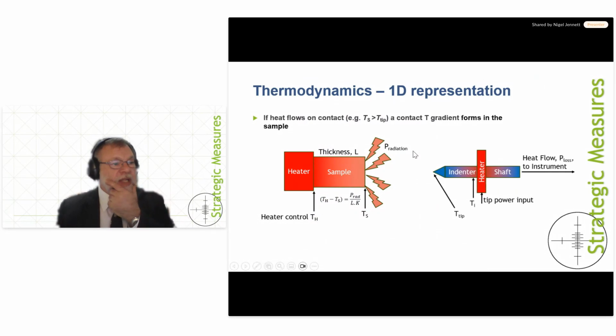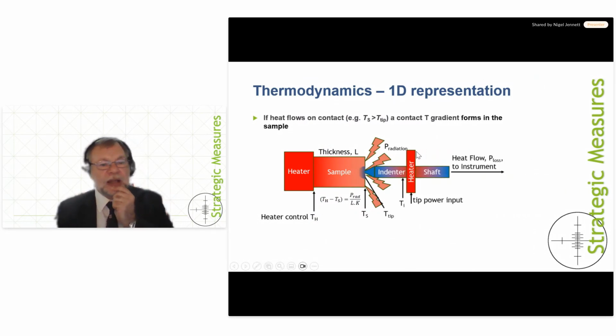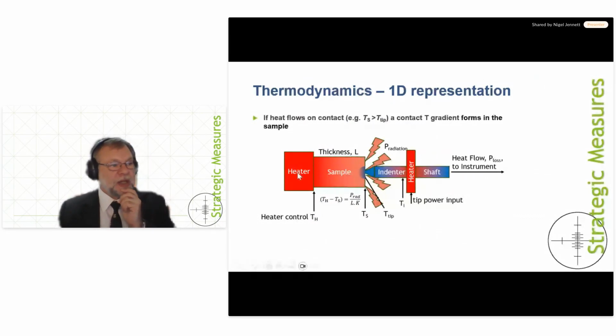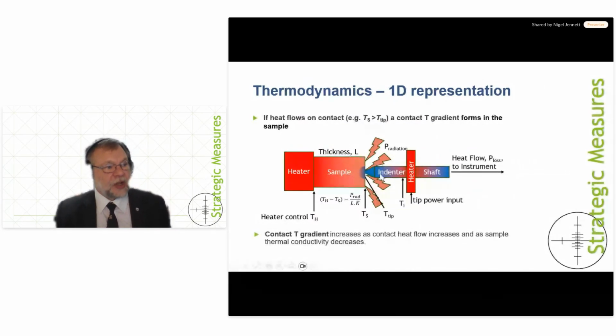So if you look at the indentation again, you have heat inside this, but your indenter tip is colder than your sample. What happens is now you suck heat out of your sample and you cause a local cooling. That's supplied by energy from the sample, because there's energy coming from the heater. The heater down here is controlling to a constant temperature, but you get a gradient across here, and that gradient increases as the contact heat flow increases and as the sample thermal conductivity decreases. So if you've got a very good conductor, then this is a small gradient. If you've got an insulator, a ceramic or something that doesn't conduct heat very well, that gradient could be appreciable. Most of the things that you want to test at high temperature may well be of that sort. So this is an issue.